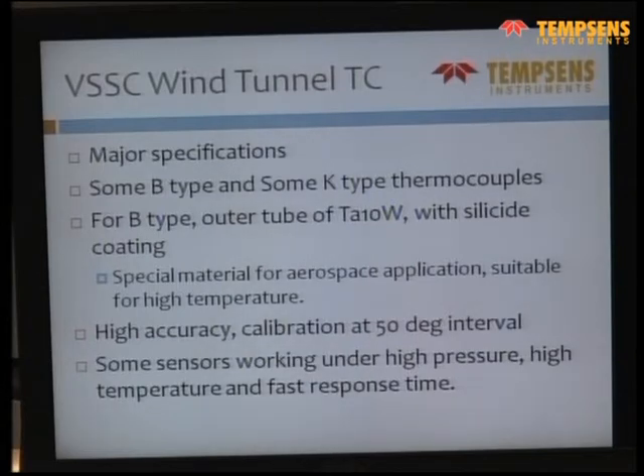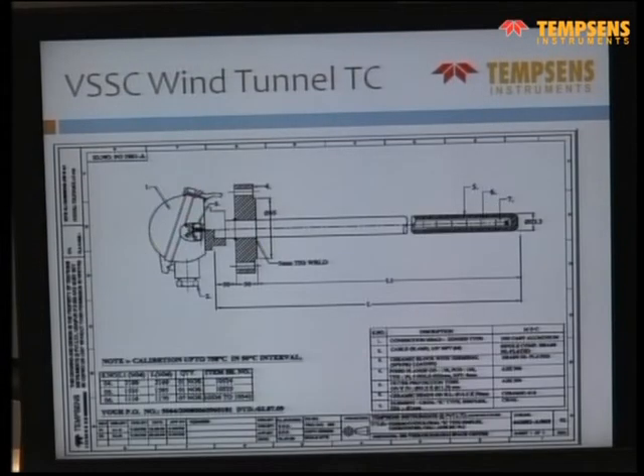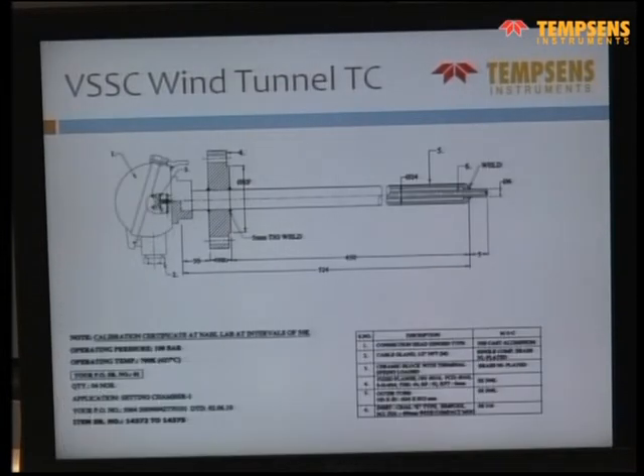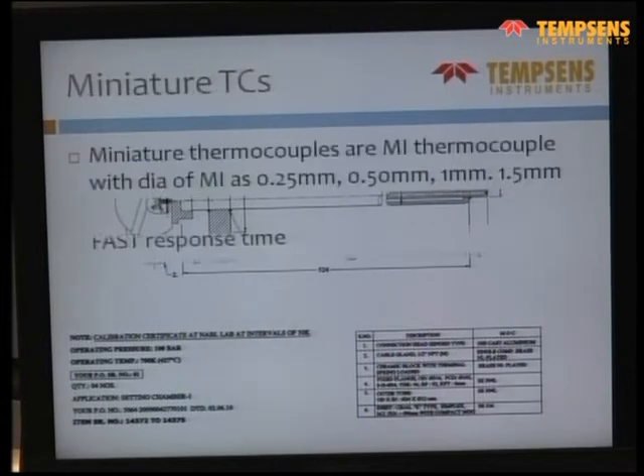So they use what's called a wind tunnel, and we made the thermowells with tantalum, tungsten, and a special coating of silicide. They were calibrated at 50-degree intervals, and they were working in high pressure and high temperature and wanted fast response time. So this is typical for the B-type thermocouple, the drawing, and this one is for K-type up to, I think, 1000 degrees or so, 700 degrees, and for fast response time we had taken the tip out of the thermowell so that it can give fast response time.